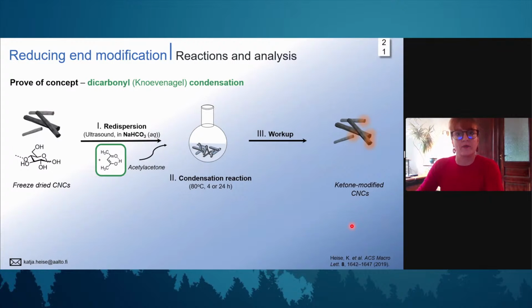So first of all, can we translate this monosaccharide chemistry to a complex substrate, so cellulose nanocrystals, and can we also use our NMR method to really analyze these products? The reaction itself is super easy. You basically just take your freeze-dried cellulose nanocrystals, you redisperse them in sodium bicarbonate solution. As a demonstrator, we used a very simple dicarbonyl compound. It's acetylacetone, or ACAC in organic chemistry language.